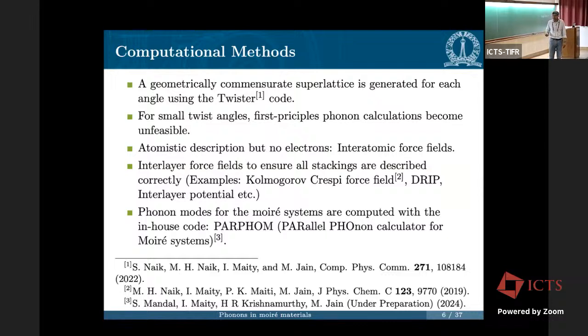Now, one thing that you have to make sure this force field does correctly is that in a given structure, you have multiple stackings present simultaneously, right? So you want to make sure that the force field that you use actually describes all the stackings correctly. And for that, people have come up with these. Kolmogorov and Crespi gave a prescription of how to construct such a force field. And there are many others. There's something called DRIP, there's the interlayer potential, and many others, right? You have to make sure that you use any one of these methods, because then you're guaranteed that all stackings are described properly in your system.